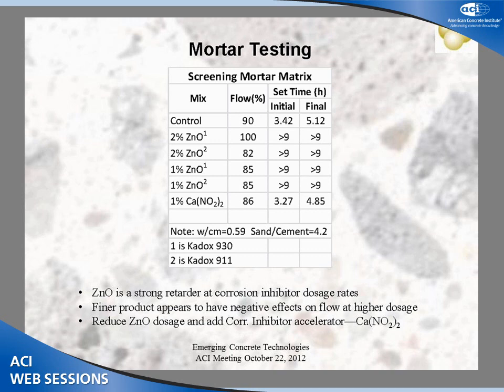The set time test with the control was fairly common. Initial and final set times were about 3.5 hours and a little over 5 hours. Quite common for a mortar mixture produced at about a 0.59 water to cement ratio. And the same thing with the calcium nitrite. Calcium nitrite, as I indicated earlier, is an accelerator, and it did accelerate the system a little bit and came in a little faster than the control.